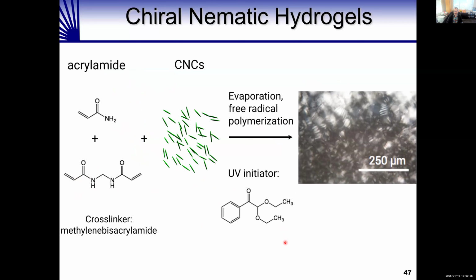Then we watch it as it dries under a polarized optical microscope. Once the cellulose nanocrystals start to form this organization, you can see this fingerprint texture arise, and so we know it's organizing. We irradiate it with UV light to initiate polymerization, and we capture the chiral-nematic organization of cellulose nanocrystals in a hydrogel.